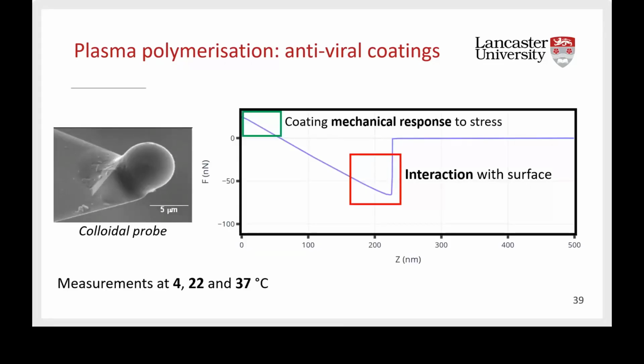To do so, we use a special AFM mode called colloidal probe AFM. This time, instead of using a tiny tip, we use a micrometer-large tip to sense the interaction between the tip and the surface as a function of the distance between the tip and the surface. What you get is a spectrum like the force versus distance that you can see in the slide. So if we start at 500 nanometers, you can see that the force is 0, meaning that when the tip is far away from the surface, they're not interacting.